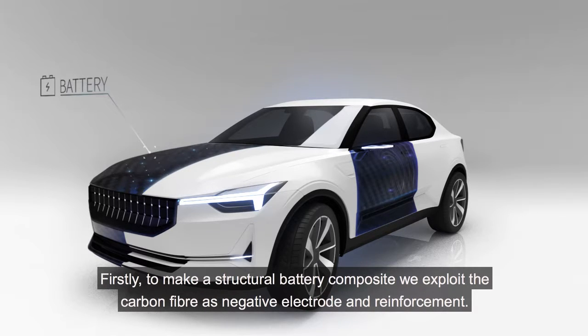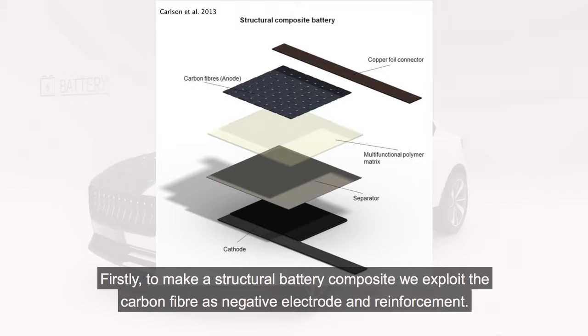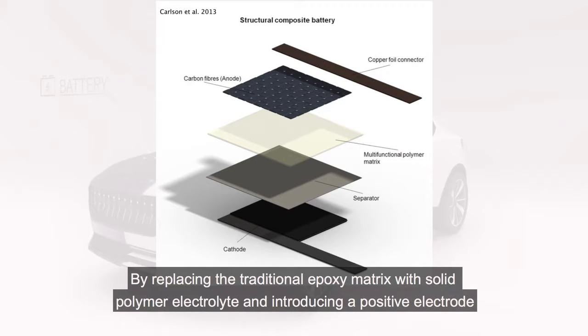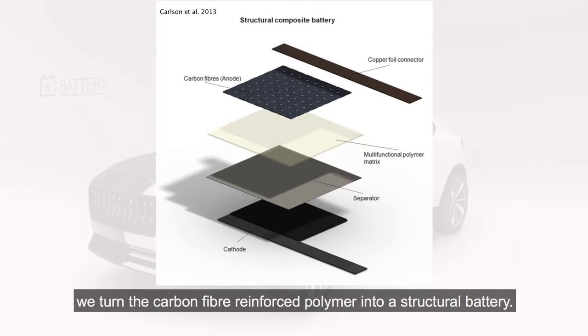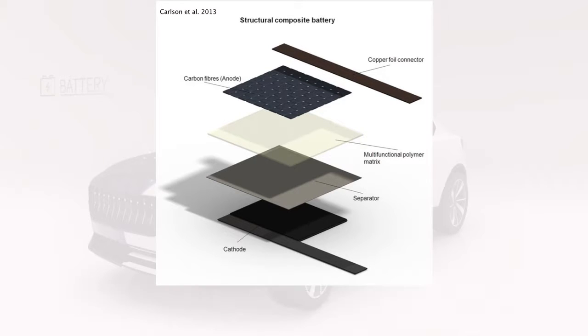Firstly, to make a structural battery composite, we exploit the carbon fibers as negative electrode and reinforcement. By replacing the traditional epoxy matrix with a solid polymer electrolyte and introducing a positive electrode, we turn the carbon fiber reinforced polymer into a structural battery.